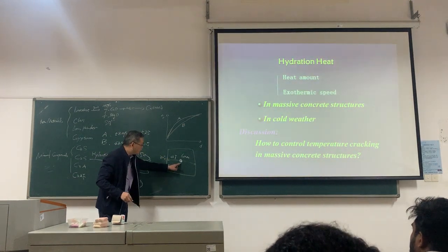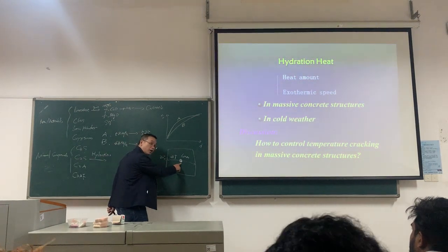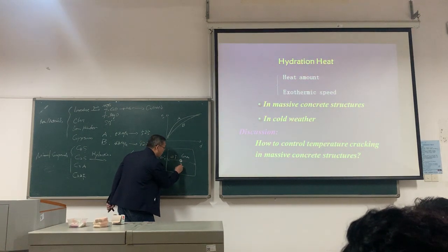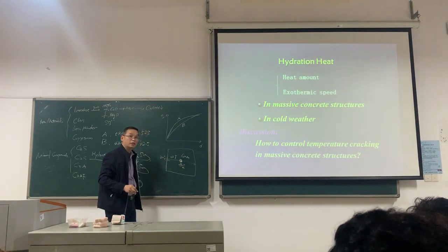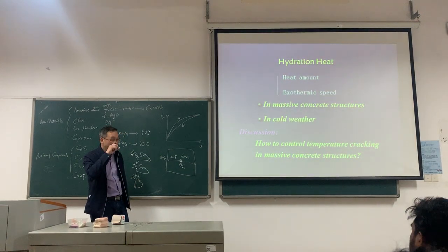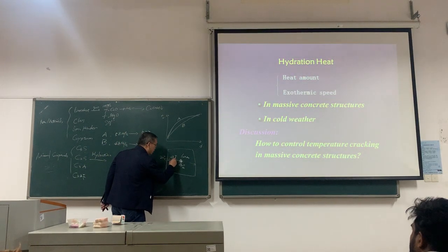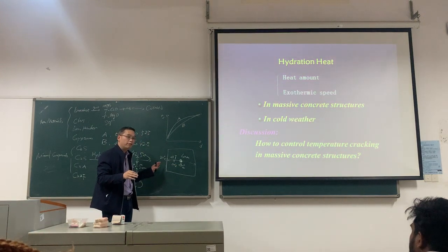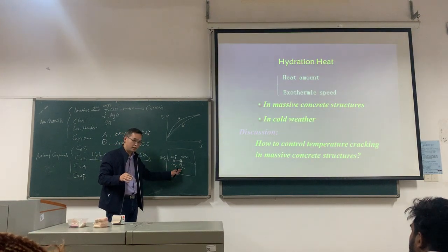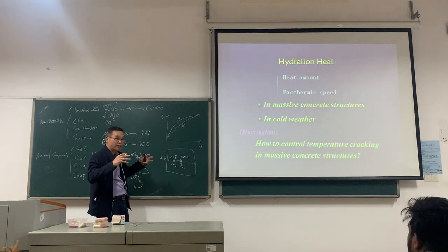But the hydration heat is gathered here, so the temperature in the structure may be 80 centigrade. So there is a temperature difference between the surface and the core, and then it will expand.